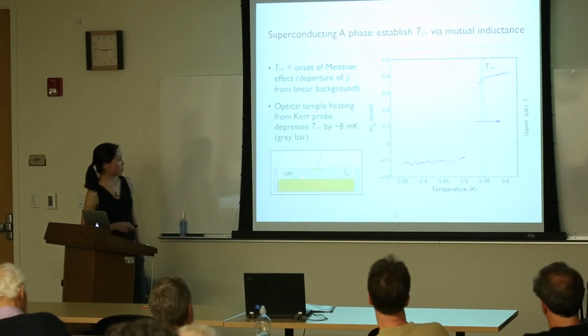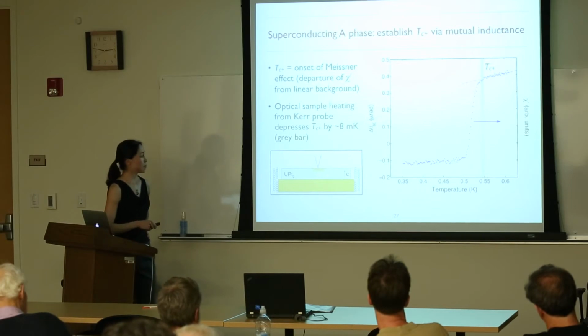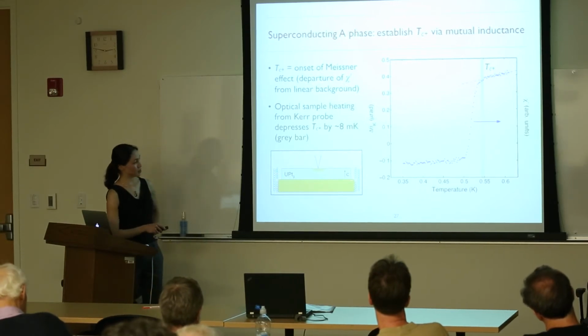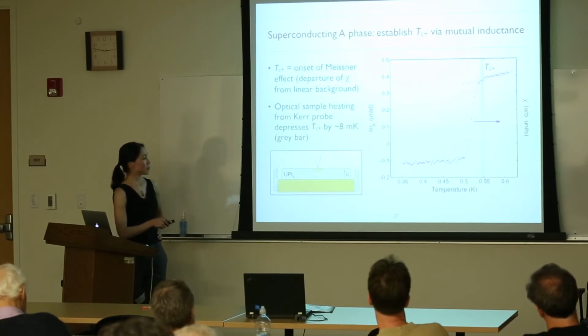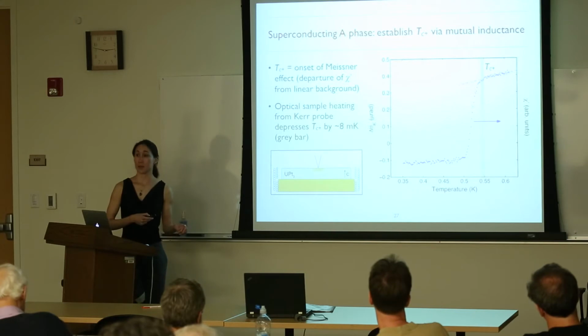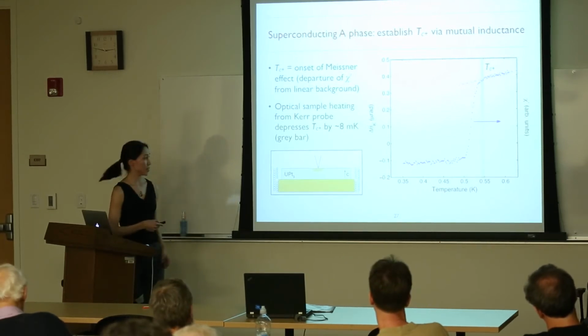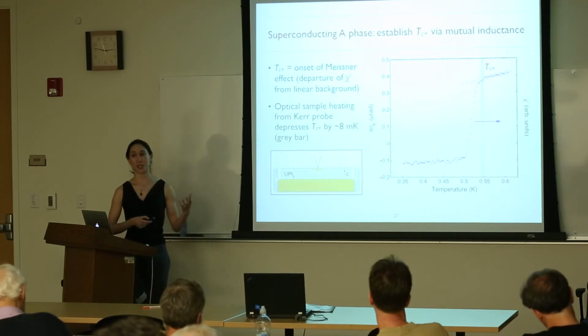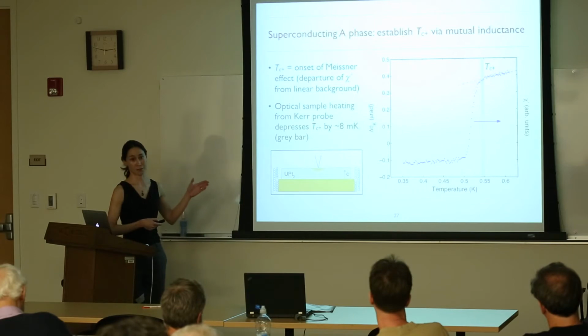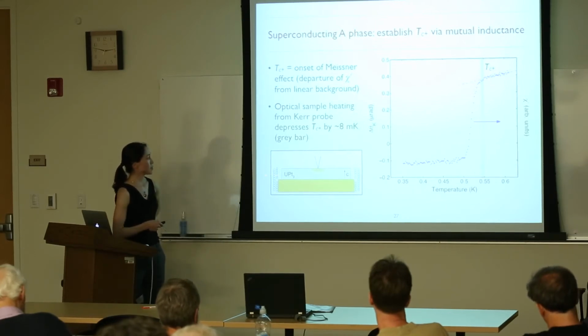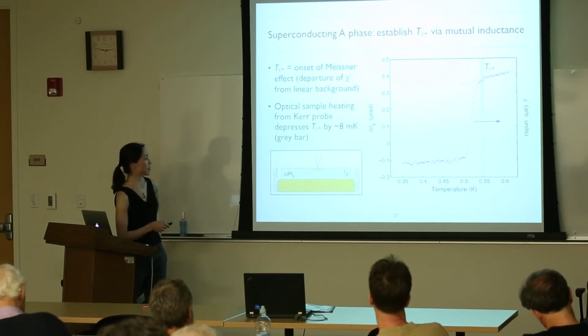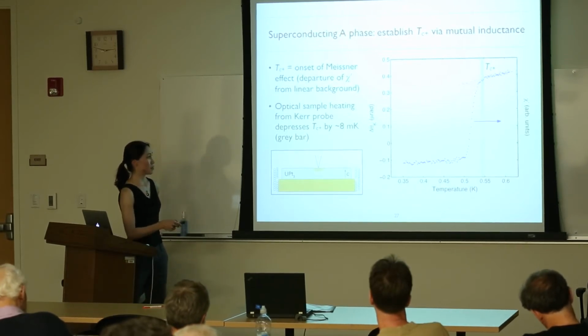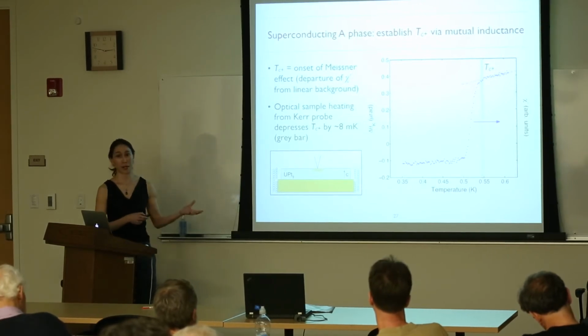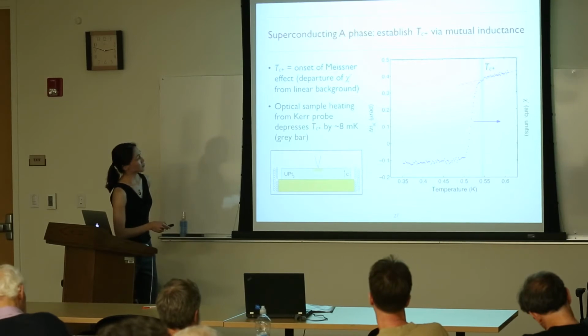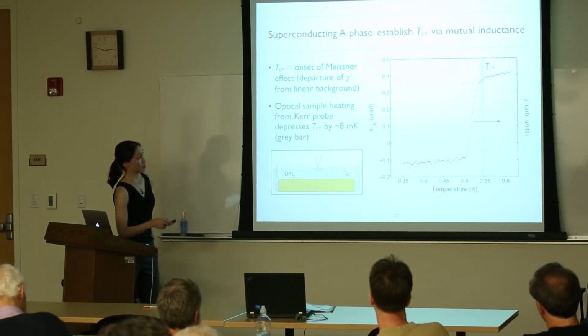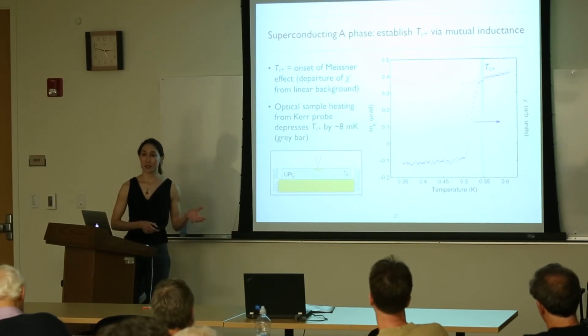That said, one thing that I mentioned a little bit, but really we do have to be careful about, is the fact that even though I'm measuring mutual inductance over this whole crystal here, when we measure Kerr effect, we're actually looking at a much smaller area that's sitting right under an optical beam. So it's possible that there can be heating caused by the beam, in which case we have to worry about whether there's going to be some shift in the temperature in the signals that we see. We can actually see this effect of sample heating even in the mutual inductance data. I can do this measurement with the light off and then with the light on, at different powers, and we can actually see this curve move. The amount of depression caused by sample heating is just shown by this gray bar here. So in the bulk, at least, it's about 8 millikelvin.